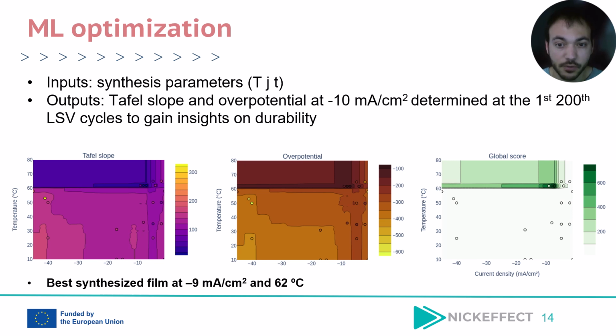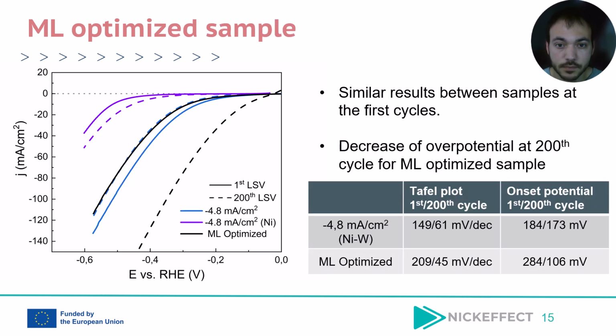So after around 30 suggested trials out of thousands of options, the best sample was the one synthesized at minus 9 milliamperes per centimeter square and 62 degrees. Here you can see the improvement versus the first suggested best sample at minus 4.8 milliamperes per centimeter square at 50 degrees in blue, and the machine learning optimized sample in black.